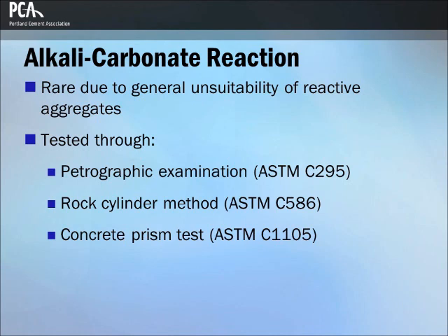Aggregates have potential for expansive ACR if the following lithological characteristics exist: clay content or insoluble residue content in the range of 5% to 25%, calcite to dolomite ratio of approximately 1 to 1, increase in the dolomite volume up to a point at which interlocking texture becomes a restraining factor, and small size of the discrete dolomite crystals or rhombs suspended in a clay matrix.